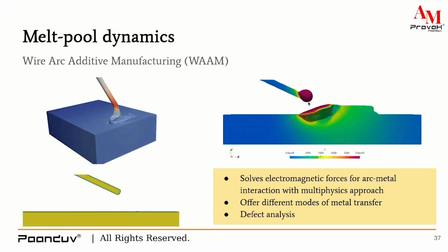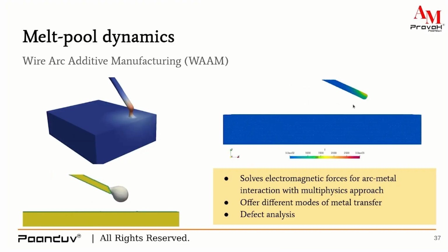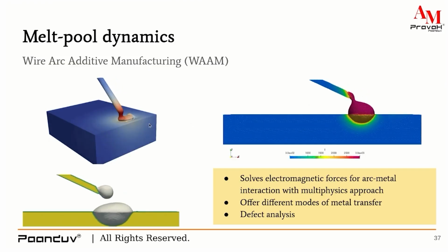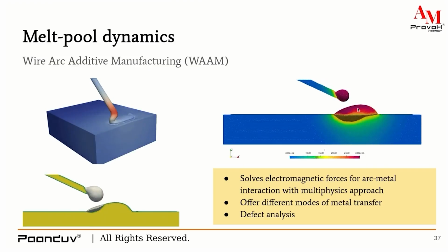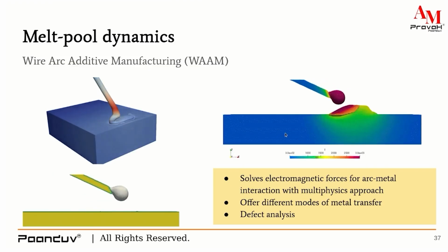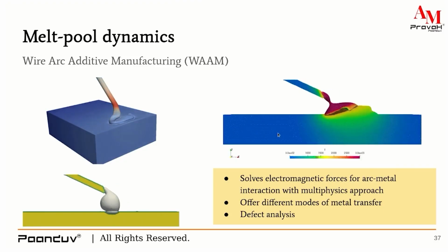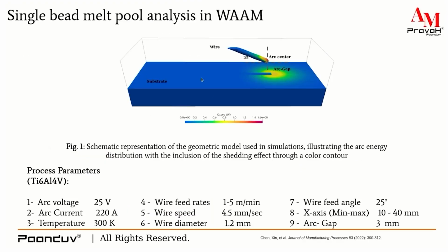Now, corresponding to this thermal history, we have taken this thermal history to the microstructure evolution method, and we have created this microstructure, and we can see the location of these fine microstructures is matching exactly with the experimental EBSD data. In fact, the larger grains evolved in this region is also matching with the experimental data.